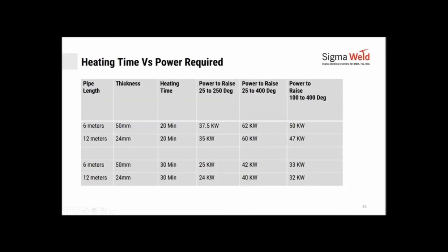This is a classic case where we check that their welding time per length was about 20 to 25 minutes. So we calculated the power in a way that one pipe could be preheated while the other is being welded, so that your more expensive equipment, that is your column boom and the welding that is happening, doesn't stay idle. The minute you finished welding the first job, you put it onto the next station, you pick the preheated pipe from before and put it onto the welding station. Put a fresh pipe which is down, put the coil on top of that pipe and start your process again. In the next 25 minutes, this pipe will be ready to weld with the same temperatures of preheating that you wanted, with the same consistency.